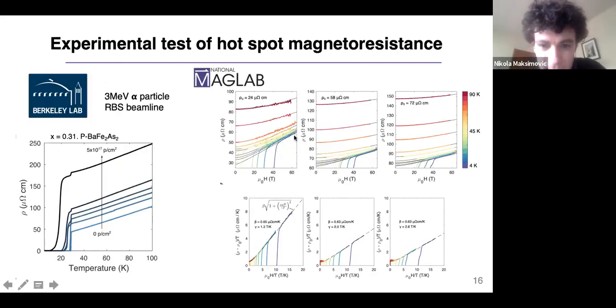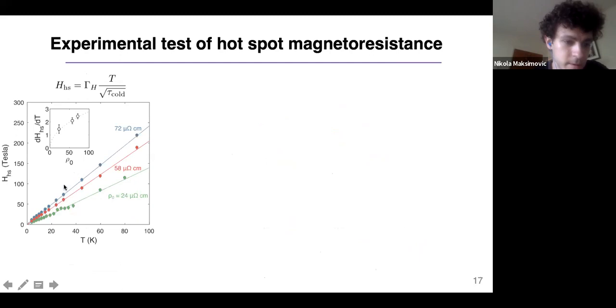So where was I? Let's see. Yeah. So okay. So we've done these calculations. Alex Koshelev did these calculations for temperature dependent and disorder dependence of the magnetoresistance, and in particular, the predictions of the model are a T-linear variation of these magnetoresistance parameters. This just comes from the fact that antiferromagnetic scattering is T-linear specifically at the hot region. And then the square root dependence on disorder. And we see a T-linear variation in these parameters, and also to some extent you can fit the disorder dependence with the square root function. Now you only have 3 data points.